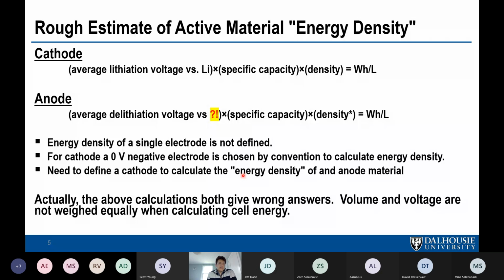And for the negative electrode, that's a little bit more difficult than the positive electrode. Typically, in research papers, if you're working on cathode materials, you can state an energy density. And typically for cathodes, you calculate the energy density as the average lithiation voltage, that would be the discharge potential in a full cell. And then you multiply that by its specific capacity and density, and then you get an energy density in watt-hours per liter. And so by convention, for cathode, you can calculate energy density taking the negative electrode as being 0 volts. For the anode, you can't do that.